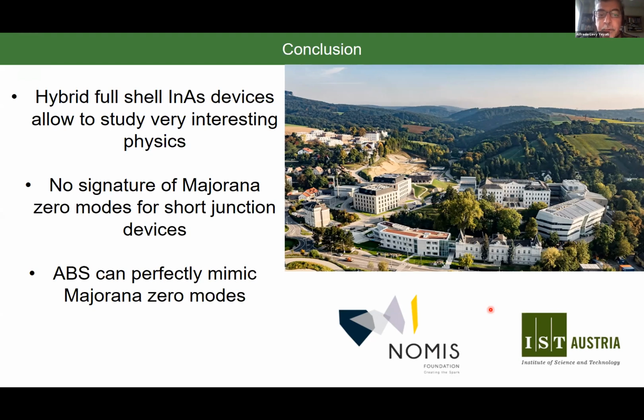From Francesco Borsoi: good morning, nice data. Have you observed enhanced conductance due to Andreev reflections in the open regime for certain junction sizes? Marco tried to move from tunneling spectroscopy to Andreev spectroscopy, and the conductance we are getting is always much lower. So it seems the transparency of our contacts is not good enough. We don't even get 2e squared over h.